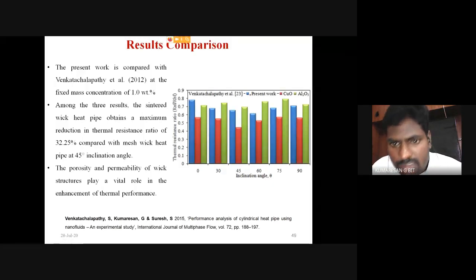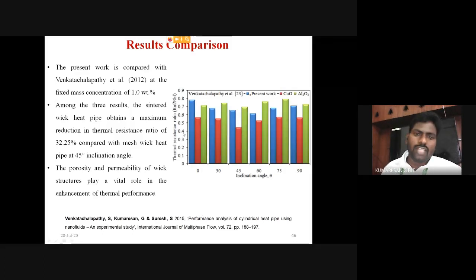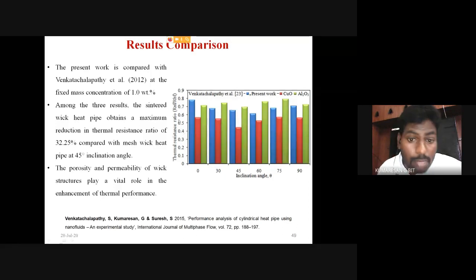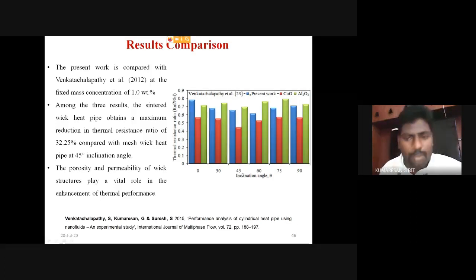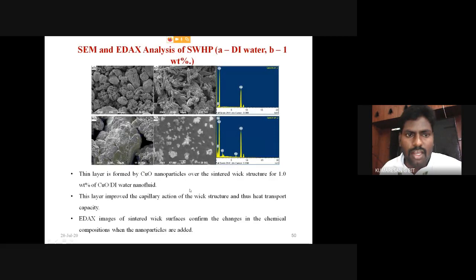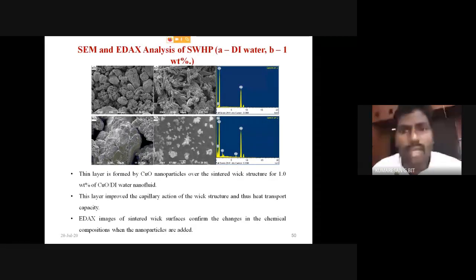Then results comparison: the present results are compared with the Venkatachalapathy et al. study. It shows the thermal resistance ratio variation with respect to the inclination angle. Then the porosity and the permeability of the wick structure play a vital role in the enhancement of thermal performance of the heat pipe. Then finally, I conducted SEM and EDAX analysis of the sintered wick heat pipe.